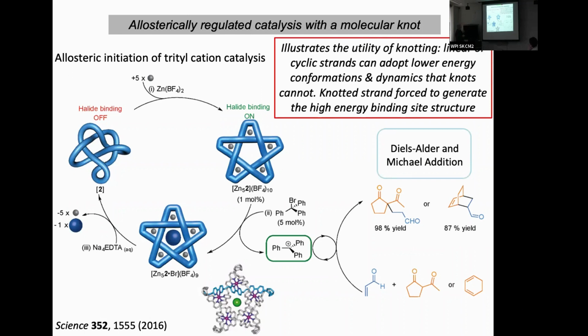If you don't have a knot here, if you just have linear helicates, they won't form any kind of cavity. So what having this knotted ligand does is it restricts the conformation and the dynamics of how these strands would normally want to adopt if they weren't in this knotted topology. So the knotted strands allow these higher energy structures to be generated because it can't adopt the lowest energy structure that you would have if you didn't have a knot here, if this was just a linear polymer or linear oligomer. And this illustrates a general property of knotting or entanglements, that it restricts conformational freedom of units.